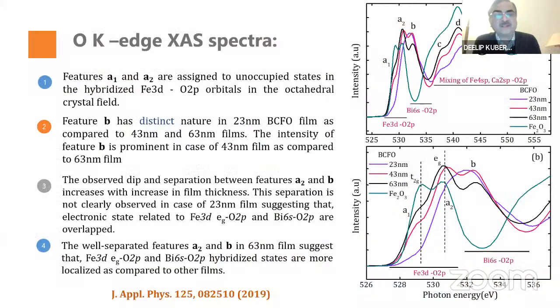After doing these measurements, we move on to X-ray absorption spectroscopy to study the electronic structure modification. What happens to the electronic structure as a function of the film thickness? These measurements were taken using the Indus-2 facility at RRCAT. So we did the oxygen K-edge X-ray absorption spectra, and we completely fitted this data. After fitting, we saw that the A1 and A2 features are assigned to the hybridized Fe 3d and oxygen 2p orbitals in the octahedral crystal field symmetry, and the feature B has a distinct nature.